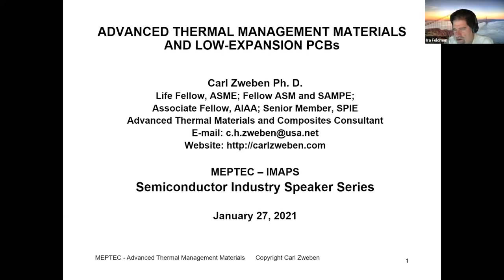Got it. On the low CTE PCBs, and I know this is general, is there an approximate cost difference between constructing, let's say, out of FR4 or switching to some of these lower CTE materials? Just any rules of thumb? Well, at this point, I only know of the one commercial printed circuit board material with a low CTE, and that is the aramid fiber reinforced printed circuit boards. I don't have a feel for the cost differential. I've never used them myself. Well, actually at GE many years ago, we did develop Kevlar 49 fiber fabric reinforced printed circuit boards, which were in production in some GE applications for a while.